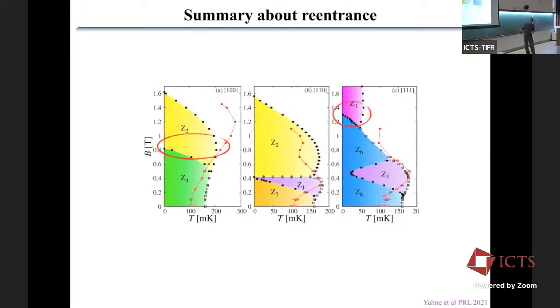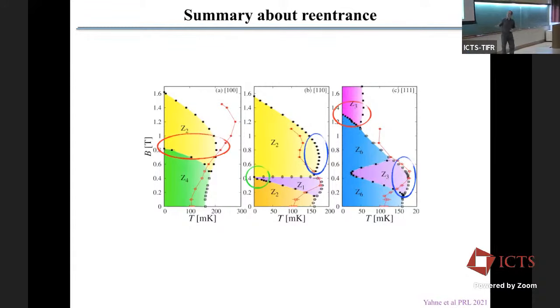This phenomenon is the same one that you have here and here. Here you have a slightly different one where you have these soft modes, but then you have a change of 3 different ground states here very fast. And then here, you have a different type of soft modes. So I'm not going to go into the details here for lack of time, but in all cases, the reentrance is connected to the appearance of soft modes and quite frequently can be attached to a zero temperature phase transition.